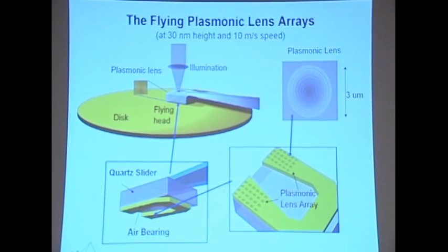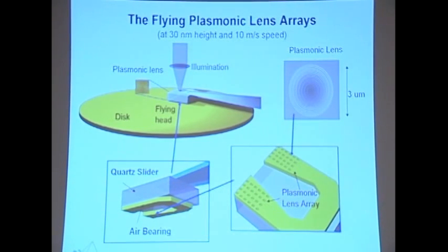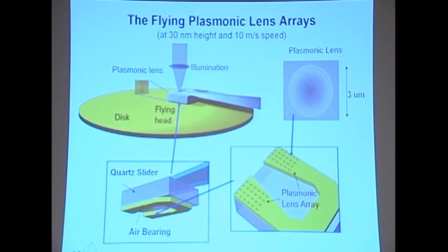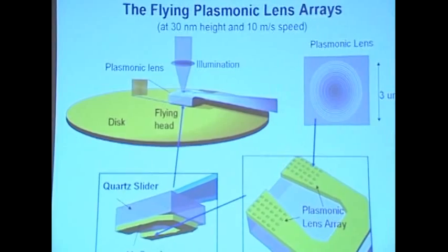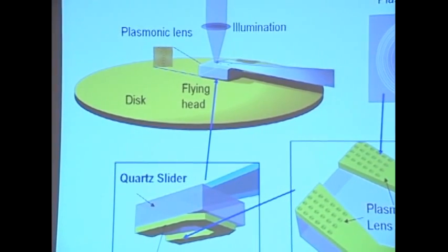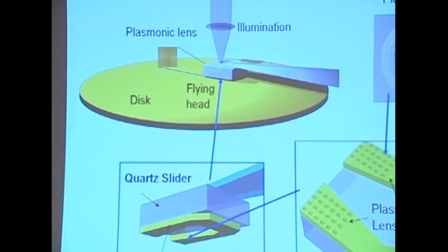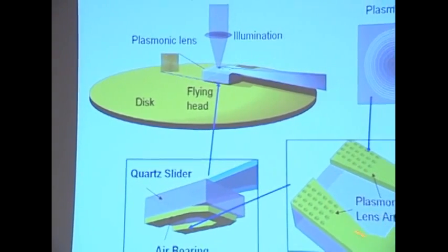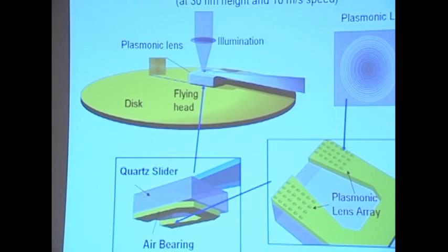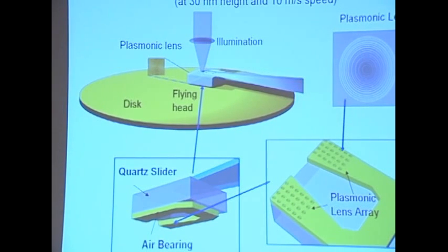One of the solutions we are currently developing is to take this plasmonic lens and fly it at high speed. The idea is to build a small flying vehicle, a small airplane if you will, that can fly at a gap of 20 to 30 nanometers. This technology is adapted from magnetic storage technology, where in the hard disk you have a flying head as well. We collaborate with my colleague, Professor Bhushan in mechanical engineering, who is an expert on air-bearing design. This small airplane has to be able to fly about 20 nanometers high at a speed of 10 meters per second.